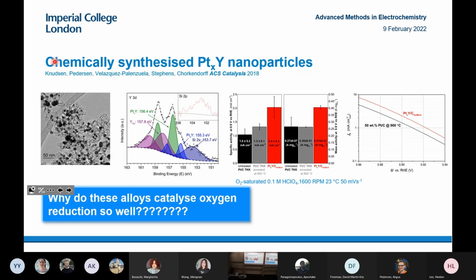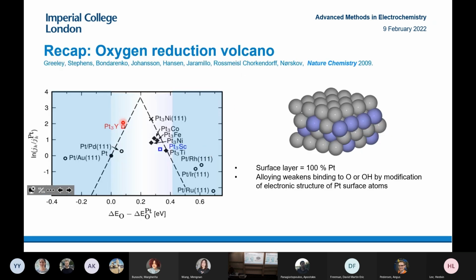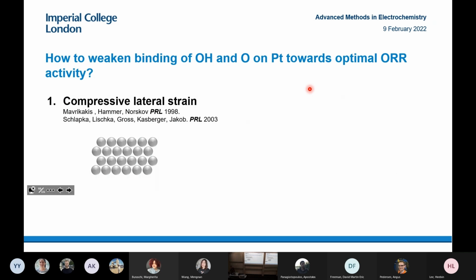So we had a theoretical prediction, and that was for a very specific surface. According to the theoretical predictions, this is platinum yttrium. What we expected was that you'd rely on a ligand effect. So you'd expect a lot of yttrium to be in the second surface layer, and you'd form this perfect single crystal type surface. There are two different effects which you could use to weaken the binding of OH and oxygen. So apart from the ligand effect, you also have strain effects.